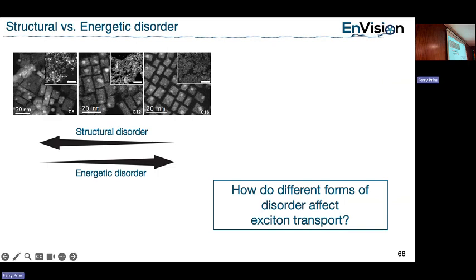And then the other problem is that with cadmium selenide—well, you can go to cadmium sulfide—but the chemistry becomes difficult depending on the material you're working with. And if you really want blue emitters, they need to be so tiny that you get into the same story as what I've told here: if you go to a very quantum confined system, adding or subtracting a single atom is going to change your bandgap.